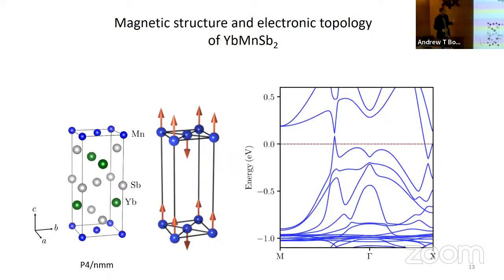Right, so now knowing what the magnetic structure is from experiment, one can calculate using ab initio techniques the band structure. You can see that we're using this model for the magnetic structure together with the known crystal structure. The chemical potential, which is the zero level here, intersects the bands at these points, and these are actually very close to these gapped Dirac cones, which were predicted earlier. So this one here is one of the Dirac cones, and this is the other one.